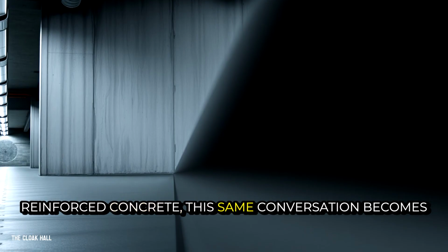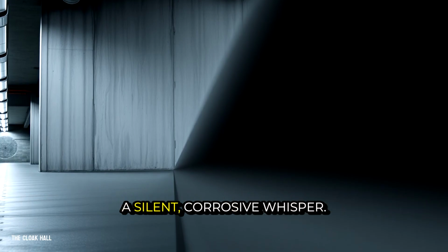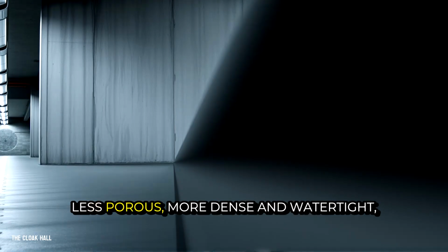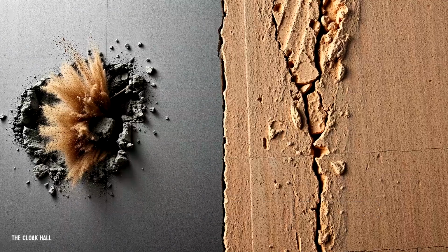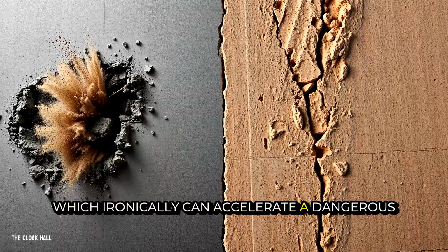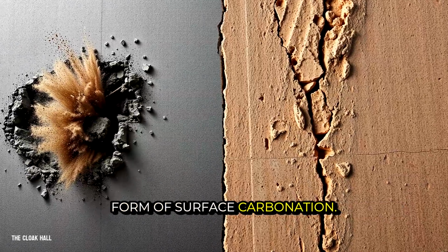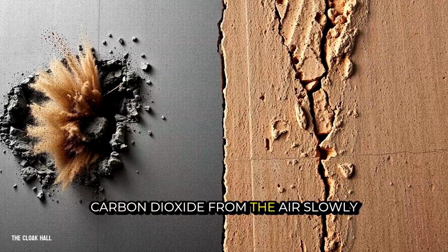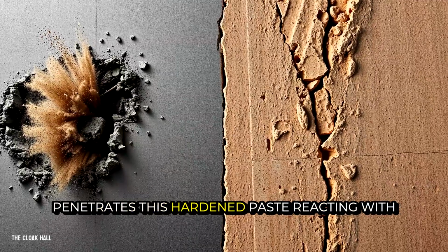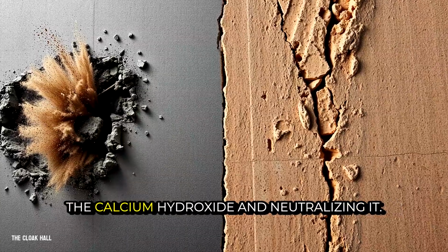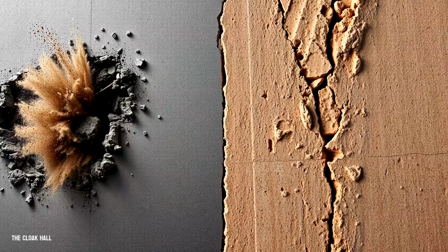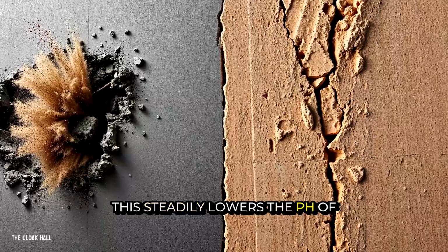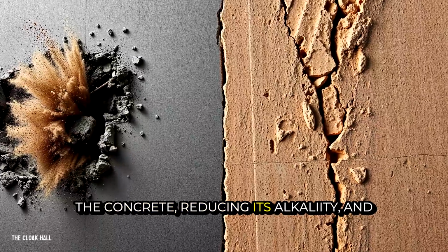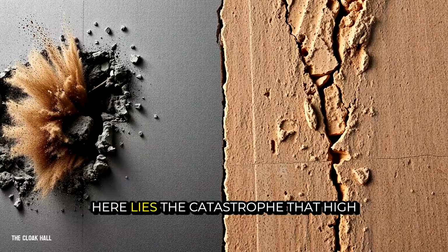But in our modern reinforced concrete, this same conversation becomes a silent, corrosive whisper. Our mixes are designed to be less porous, more dense and watertight, which ironically can accelerate a dangerous form of surface carbonation. Carbon dioxide from the air slowly penetrates this hardened paste, reacting with the calcium hydroxide and neutralizing it. This steadily lowers the pH of the concrete, reducing its alkalinity, and here lies the catastrophe.